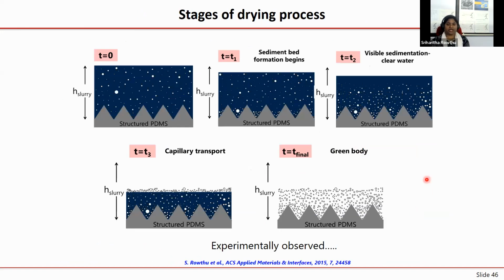I said that the drying was very important to understand, right? So initially, when you had poured your slurry, this is actually your slurry of water plus polyacrylic acid, and these white dots are your aluminum oxide nanoparticles. This slurry, when you have poured it on your PDMS, which for example contains these sort of textures, it could also be dimple type, and this is more for a schematic diagram. To begin with, at time t equal to 0, this is very nicely suspended.